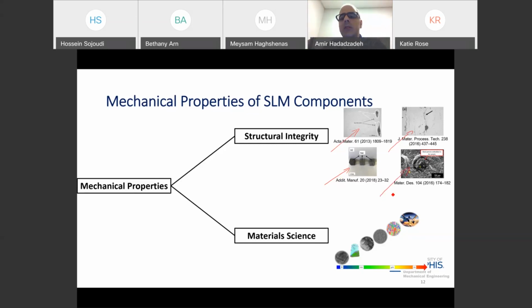And also another aspect is reducing the other types of defects like inclusions. So by reducing and controlling those defects, we can ensure structural integrity to have a strong component. But another point of view here, which I'm interested in, is studying the material from a material science point of view. To look at the microstructure of the material, to see how that microstructure at different length scales, from atomic scale, as you see here, up to sub-millimeter scale, how these features will affect the properties.